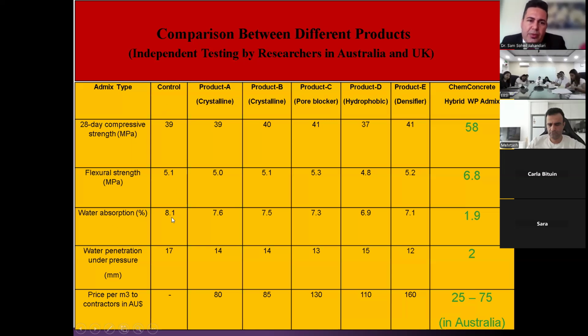And also in terms of water absorption, control concrete had like 8.1% water absorption. The first crystalline had 7.6, 7.5 for second crystalline, 7.3, 6.9, 7.1. So in general, they reduced the water absorption by say around 10%. But our ChemConcrete waterproofing admixture reduced it from 8.1 to 1.9. So you can see that huge difference between the effectiveness.